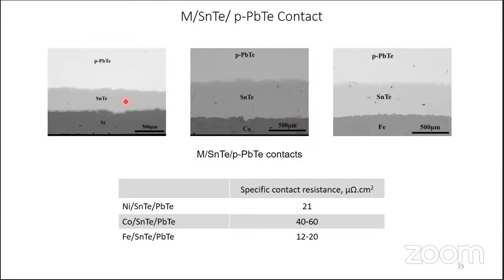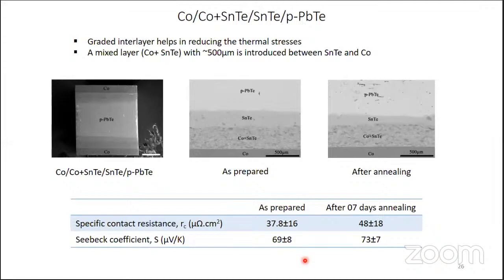So to improve it, we tried tin telluride as a diffusion barrier or contacting material. And then finally, we ended with a configuration like this, which gives a very thermally stable metal semiconductor joint. The contact involves cobalt as an electrode, with cobalt tin telluride as a first barrier and tin telluride as a second barrier, and then you end with the actual material. So this is very stable.